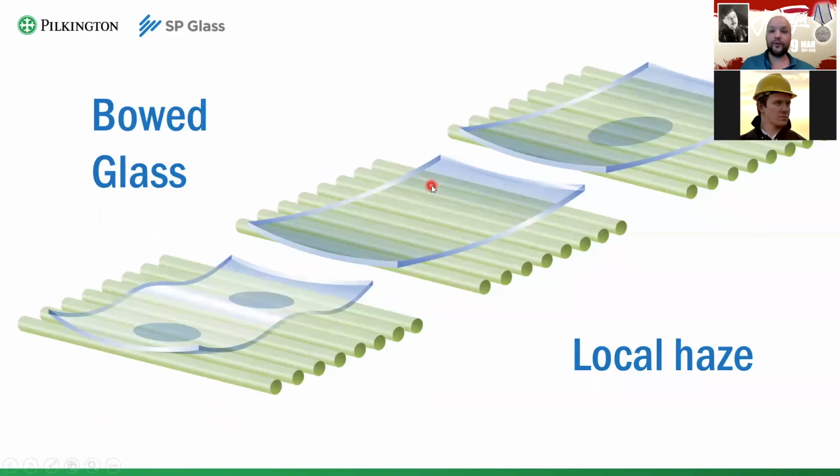And now we are moving to the proper tempering defects, which are defects without any discussion. If you're tempering your glass properly, you need to heat it properly. And properly heated glass in the tempering furnace is lying flat. It should not bend a lot. Like, it should not be like this or like this or any other configuration. Some of them you might see.